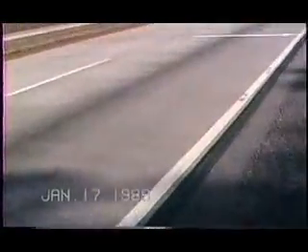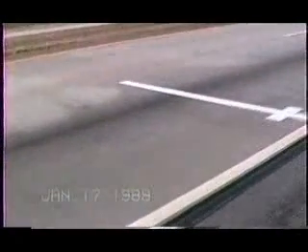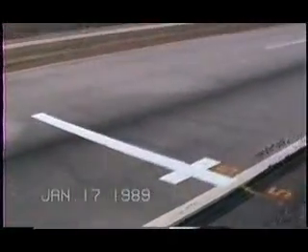I mean, this is taking a pattern that almost looks like alligator cracking, or fatigue cracking, although it's starting from the top down, and one wouldn't suspect that fatigue would begin in that direction or work in that direction in a continuously reinforced concrete pavement. There is still some truck traffic out here, as you can tell from that passing.